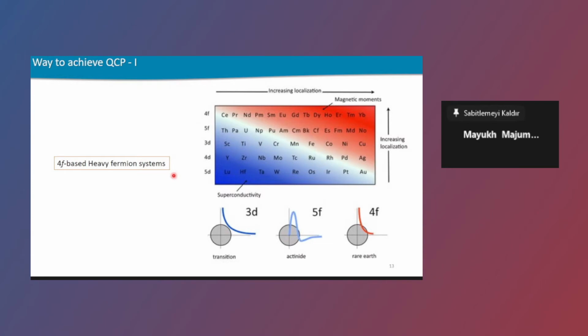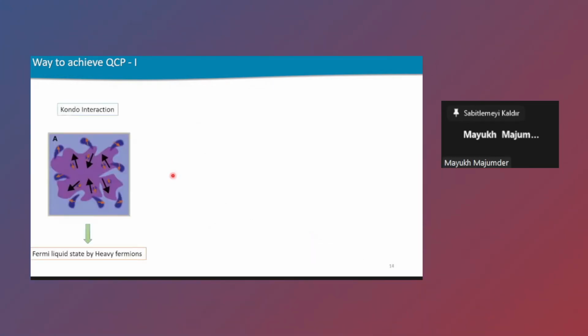In this sort of systems, at rather low temperature, the 4f moments couple with the conduction electrons, and they form many-body singlet type of states. As a result, the conduction electrons quench the moment of the 4f moments. So at further lower temperature, there is no long range magnetic ordering, but the system shows a Fermi-liquid type of heavy fermionic state. This is nothing but the Kondo interaction, and you can easily imagine that because of the quenching of the 4f moments, when the Kondo interaction dominates you have a lesser chance of having long range magnetic order.